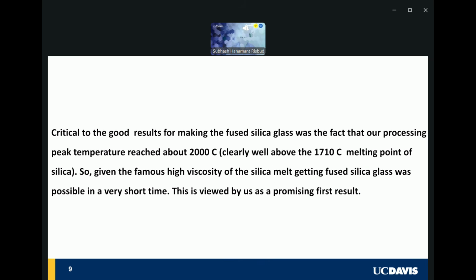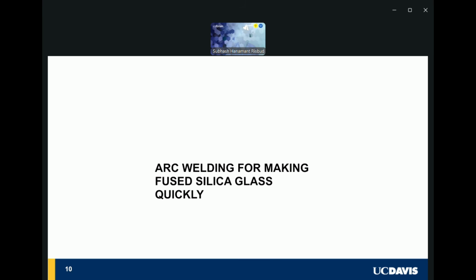So critical to the good results that we got is that when the peak temperature, which we estimate to be about 2000 centigrade, even though it's for a short time, which is well above the melting point of silica, as you must know, and given the viscosity of the silicate melt being what it is, we thought it was a promising result that we could reach a temperature like that, even though for a short period of time. So that gave us a good piece of initial glass.